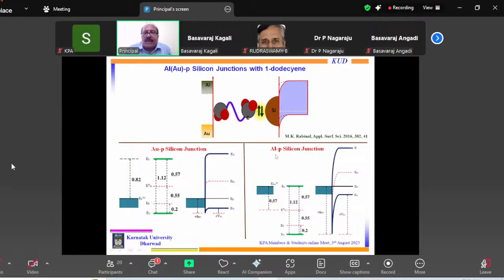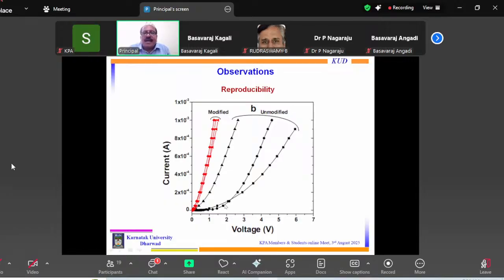But if I go to aluminum and p-type silicon and again do the same thing, then what I expect is a large barrier height. So it means if I take aluminum and p-type silicon, I expect a large barrier height. And if I take gold and p-type silicon, I expect a low barrier height. So if I simply take p-type silicon and gold, and p-type silicon and aluminum, and try to make Schottky junctions, I expect a large barrier in the case of aluminum, and a low barrier in the case of gold. I will come back to that point.